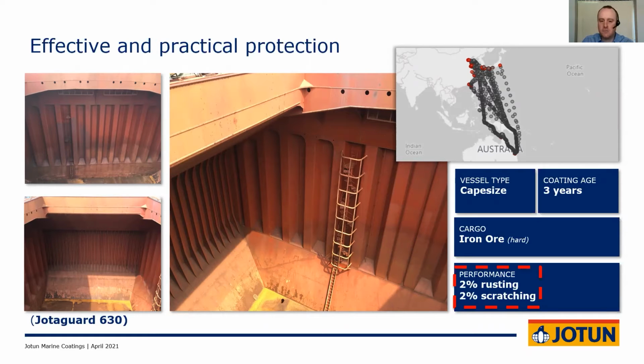And therefore, minor repair being needed at this stage, meaning that the vessel can go back into service very quickly after minor repairs and low cost, and keep going with that same cargo hold coating until the special survey, when perhaps some more significant refurbishment might be needed.